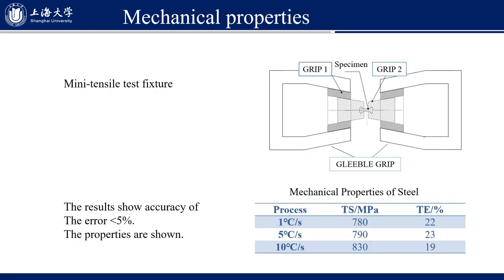This is the mini tensile test fixture developed for the hot rolling simulation test specimen for mechanical property testing. With the test result, we can see for 1 degree C per second to 10 degrees C per second cooling conditions, the tensile strength is around 800 MPa and the total elongation is around 20%. This result shows the accuracy of the mini tensile test fixture, and the error of the test is within